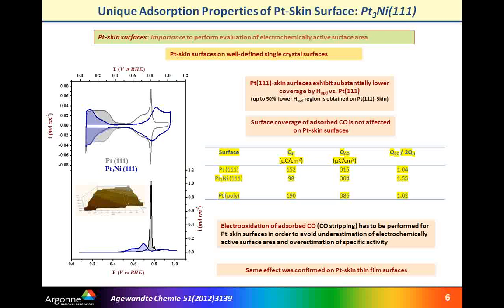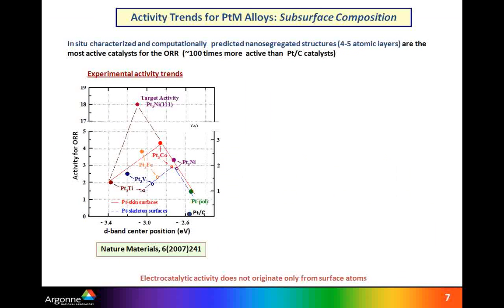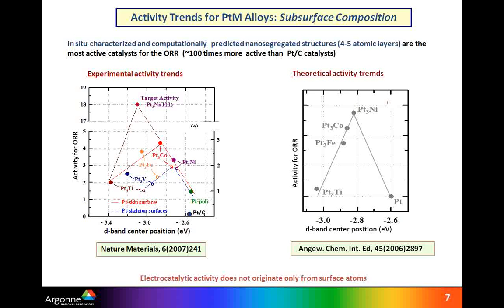Now, based on this, at least in our case, we simply used the geometry of extended surfaces to establish catalytic activity. And as I said at the beginning, we are always focusing on the trends. We are trying, based on trends, to understand what is going on during the reaction. I'm not going to go into details, but I want to point out once more that platinum-3 cobalt and platinum-3 nickel do have unique catalytic activity. We assign this to unique nanosegregated domains, which are also confirmed with the DFT calculations.